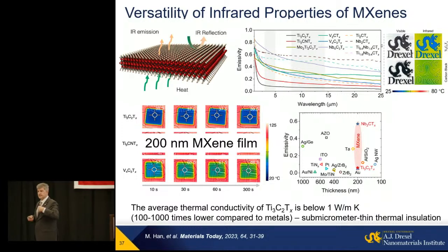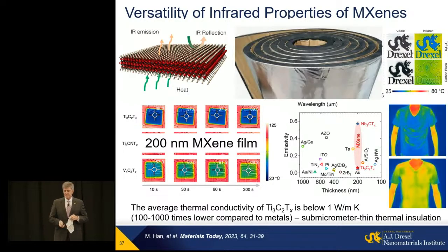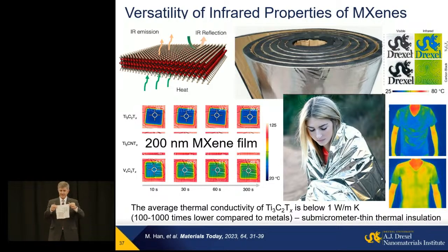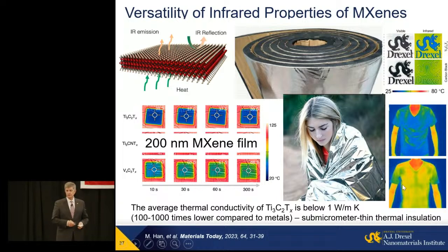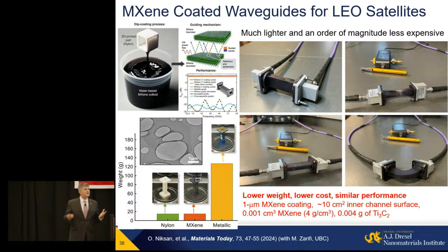Or imagine a silk dress like I showed to you that is coated with MXene, and it keeps you exactly as warm as thick insulation or as a space heat shield that is used here. So you can have a silk dress, and it will be as warm as a fur coat because you're not losing energy through radiation, and at the same time, it has very low thermal conductivity. And of course, it provides infrared stealth. This is a t-shirt that my student washed simply in MXene solution, and you see now it looks cool, so there are no temperature losses from the body happening here. So I think those just give you a glimpse of applications, very, very different.